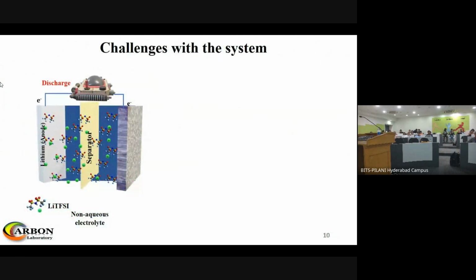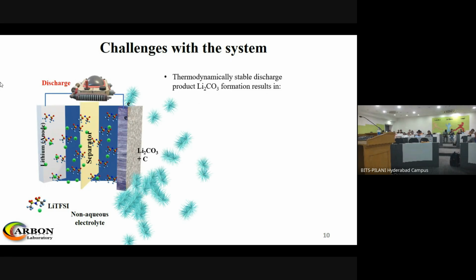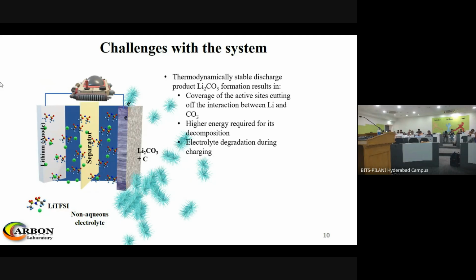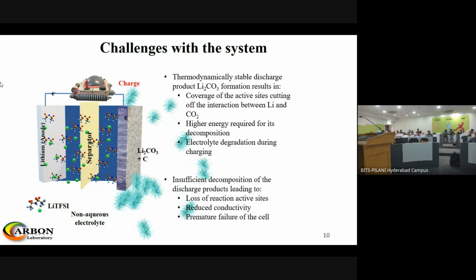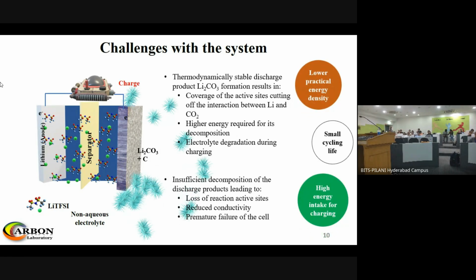Now with this, what are the challenges involved in the system? Let's talk about that. As I mentioned, lithium forms lithium carbonate and carbon, and this lithium carbonate gets deposited on the surface of the cathode. This solid product of lithium carbonate and carbon hinders the further possible active sites for the reaction. Not only does it hinder the path, but there is another challenge: lithium carbonate is a very thermodynamically stable compound. It does not dissociate easily in a reversible way. That's where we need an efficient catalyst, so that we can push the reversible reaction and have reversibility of this system.